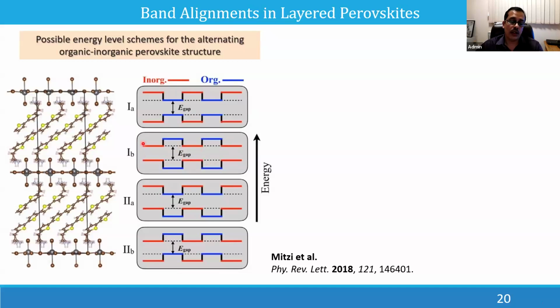Normally you will see a type 1B band alignment for a perovskite structure, because both the conduction band minimum and valence band maximum are contributed by the inorganic components, like bismuth or lead or iodine and that kind of structures. But if the conduction band minimum is contributed by the organic component, the blue one, and the valence band maximum by the inorganic one, then you have a type 2A structure.